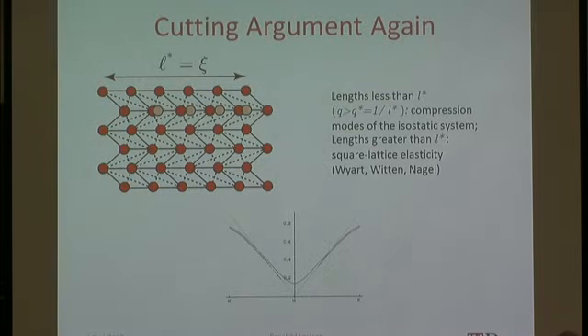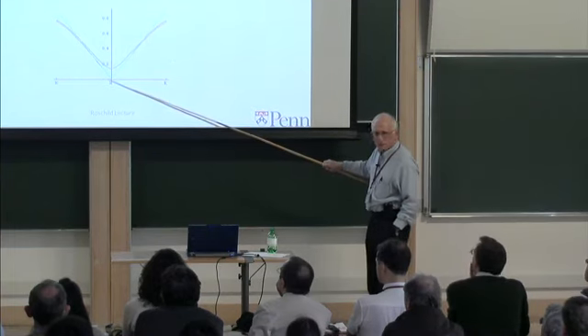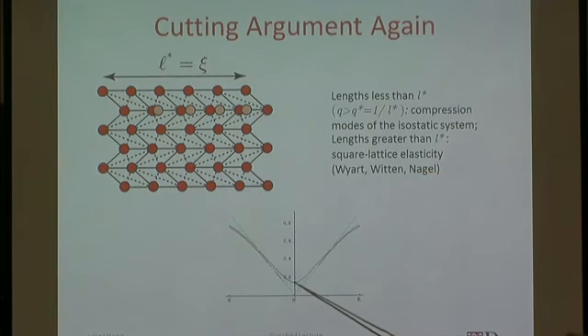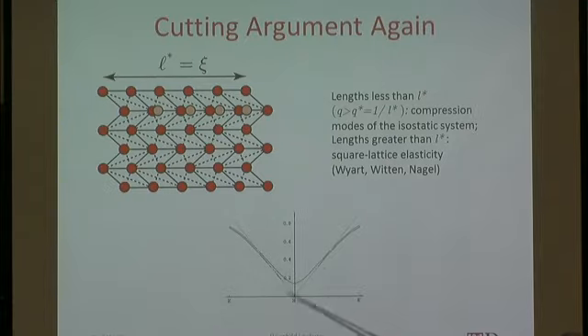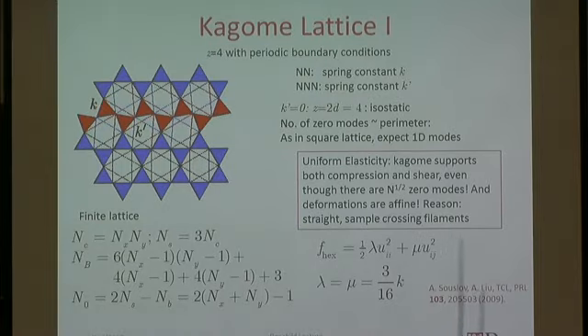And the cutting argument works perfectly well here. If I have a very small sample, if I cut out a small part of the periodic system, then the actual dispersion follows very closely that of the isostatic lattice. On the other hand, if I'm much larger, then I see the gap. So just by looking at this picture, you get exactly what Vitelli predicted. And one of the reasons is that the states of self-stress are the same, really, as the displacements of the lattice without a boundary. OK, so let's go to the Kagome lattice.